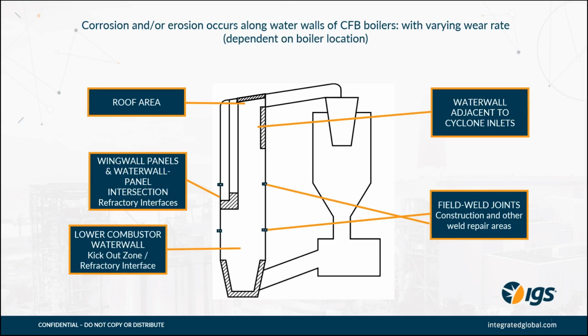So starting in the lower combustor, obviously, this is a well-known wear zone in CFB boilers, be it the high volume of ash and fuel, the turbulence from the bed, the fluidization, ash being propelled airborne and sliding back down the tubes, transferring heat as it slides across the construction and field weld joints. Obviously, these joints, if not ground down properly, can be a site of localized erosion. Due to tube fit up and alignment, there can be localized erosion that changes tube to tube.